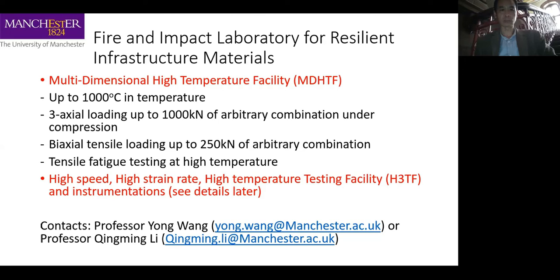The first one is what we call the multi-dimensional high temperature facility. In this case, we heat materials up to about 1,000 degrees, and then we apply loads at the same time in different directions, multi-directions. So we have a testing facility to apply 3-axis loading up to 1,000 tons, 1,000 kilonewtons in 3 directions for compression, and then we can also do tensile testing in 2 directions, biaxial loading. And for the tensile testing machine, we can also then do high temperature fatigue testing as well. So that's then the first facility.